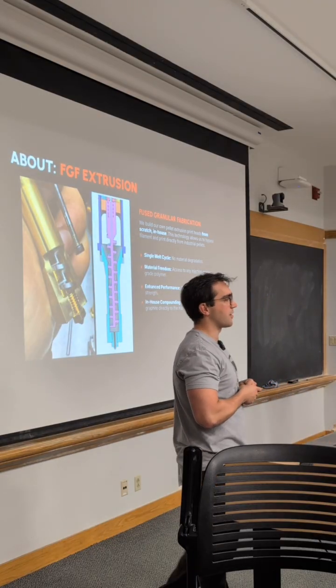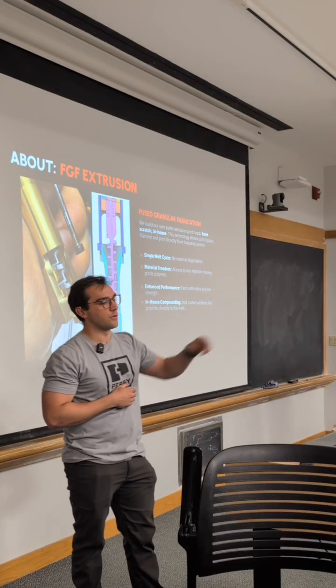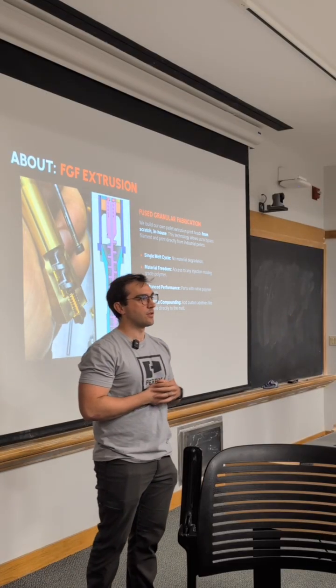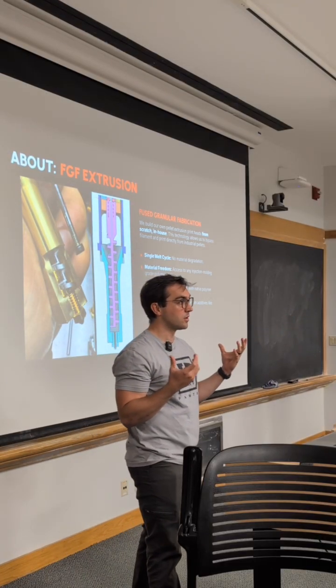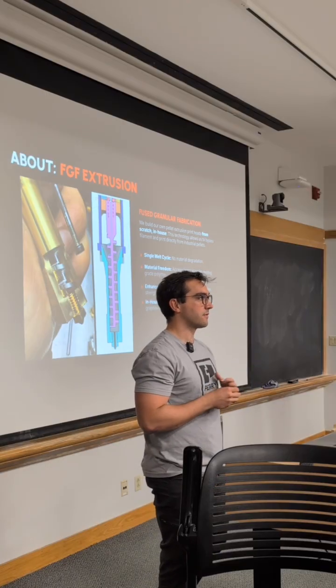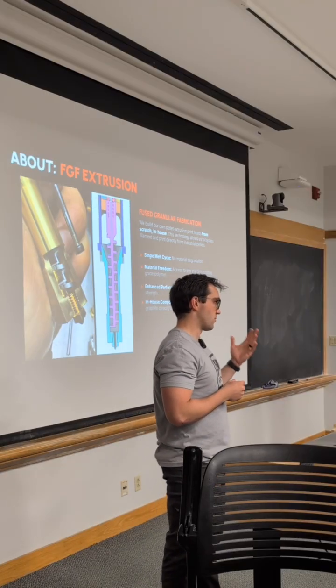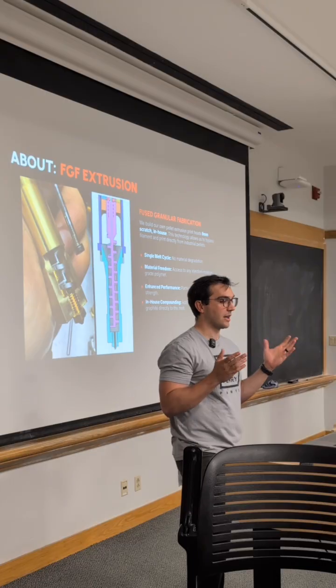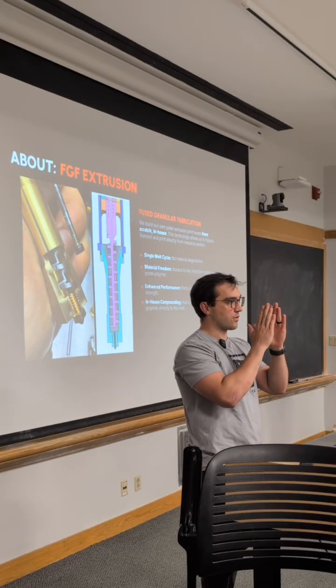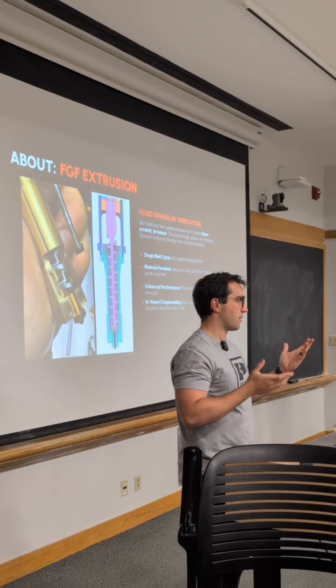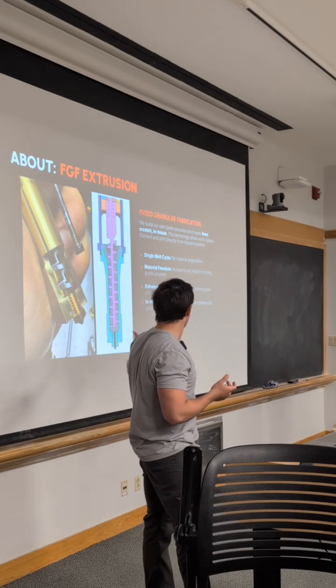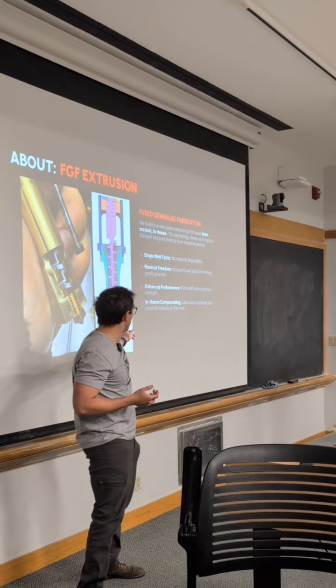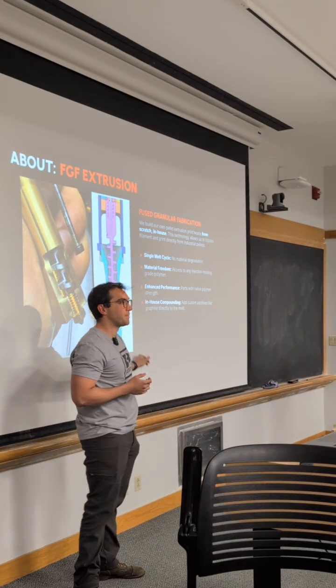I included a little cross section. We're actually passing around the barrel and the screw right now, but you can see we use a zero compression screw, which is a little counterintuitive. A lot of extrusion and injection molding processes use a high compression screw, meaning that the core of the screw tapers outward. We found that we had much more repeatable and reliable results with a zero compression screw. So that root remains the same.